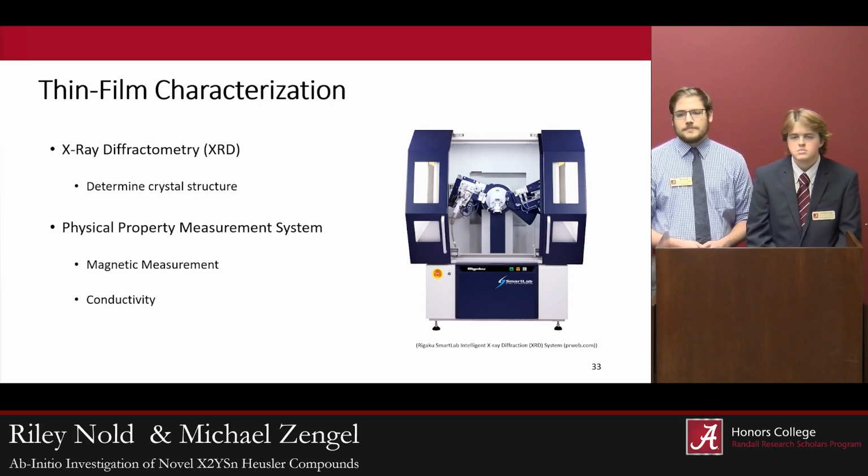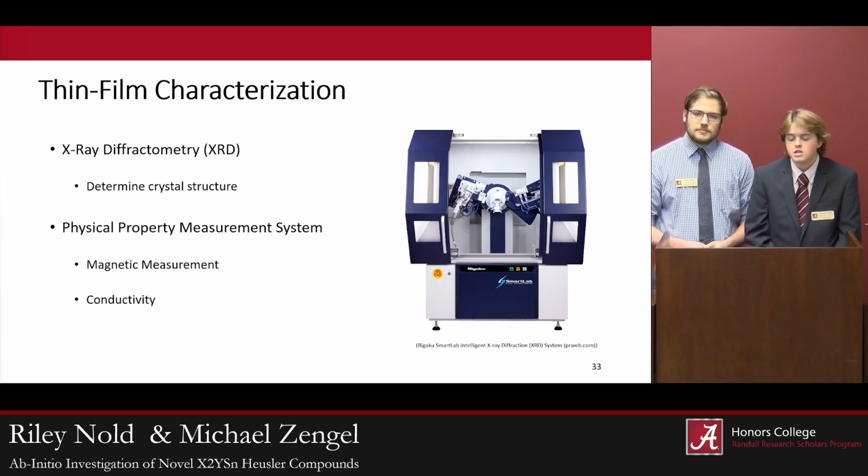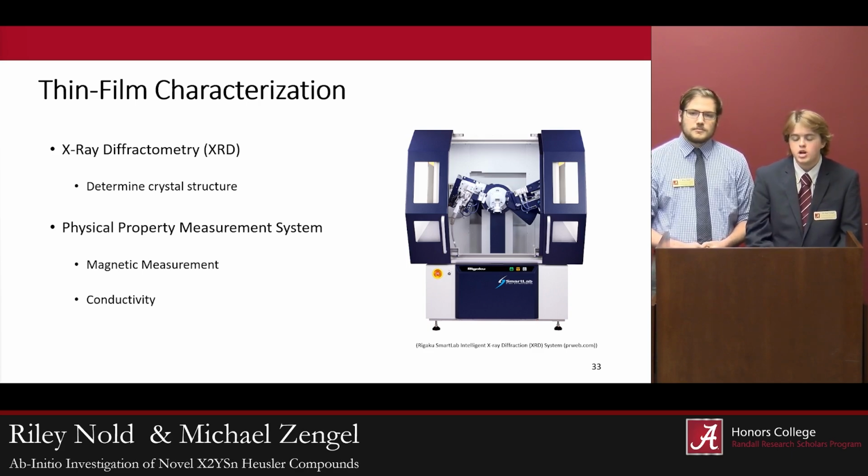So throughout the presentation, you mentioned that there were two distinct structural phases. How do you know that it wouldn't form a different type of phase? So in short, it's not entirely certain. These calculations do assume a perfect crystallinity. However, by the control of certain environmental variables when these materials are grown, we can ensure that this primary structural disorder, the site swap disorder, is the primary mechanism of structural properties within this material.